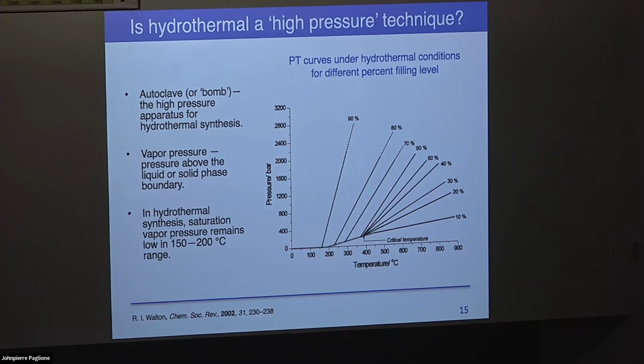You can see that these percentages here are what's called the filling fraction. It's basically what fraction of the closed container you are filling up. Once you get to high filling fractions or very high temperatures, or a combination of both, your pressure can increase very, very fast. This helps you design experiments, if you think you need very high pressure to form the phase you want, but also for safety considerations. You don't want to use a 90% filled autoclave that can only hold 400 bar of pressure at 300 C, or you'll have a bit of an explosion or something bad happen in the lab.